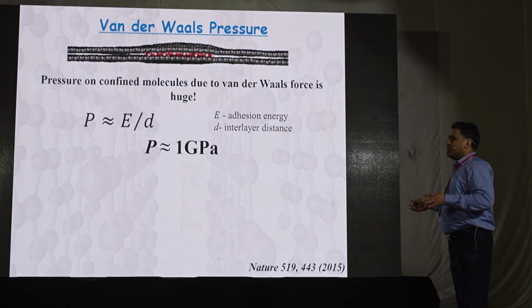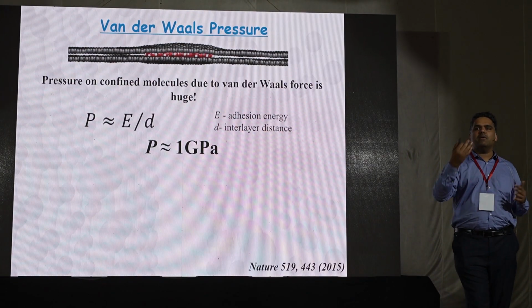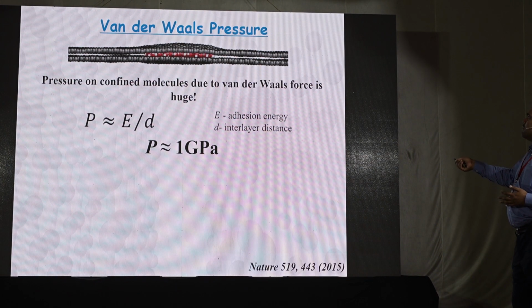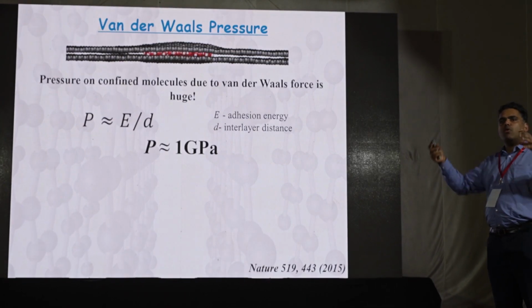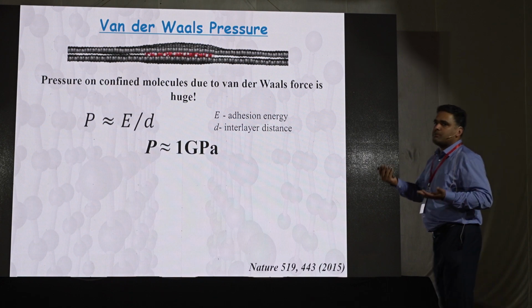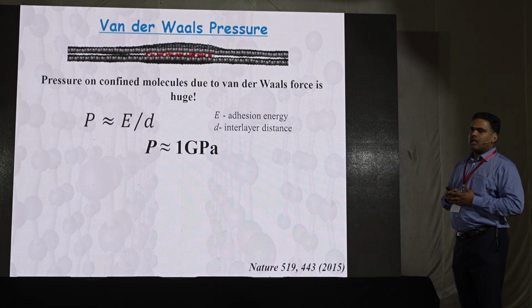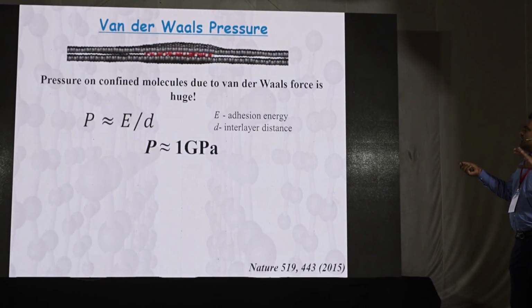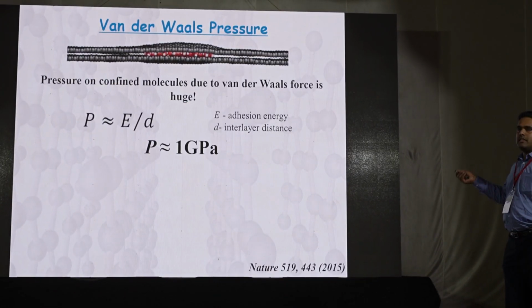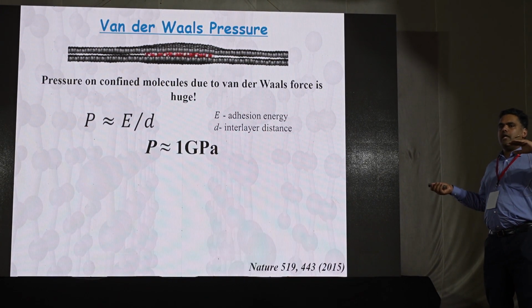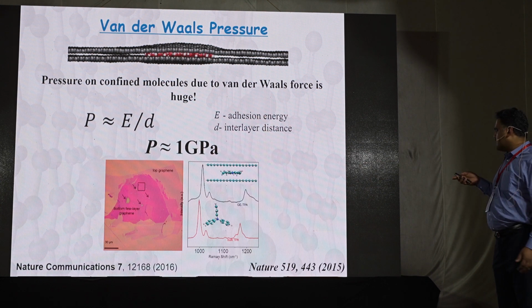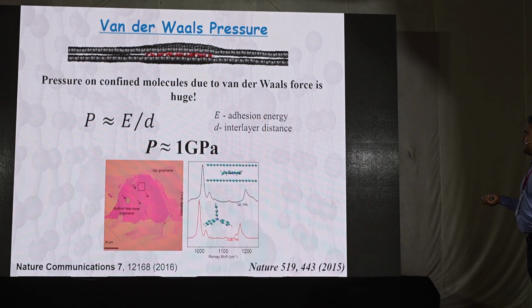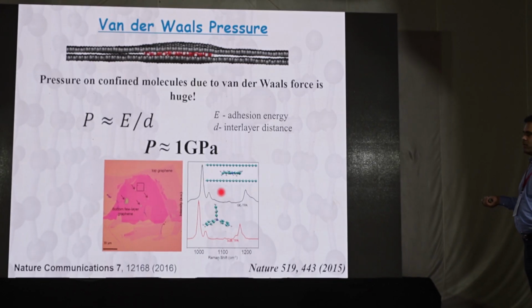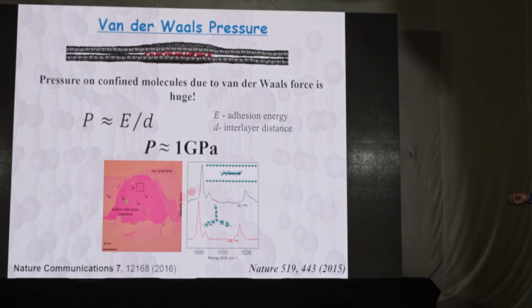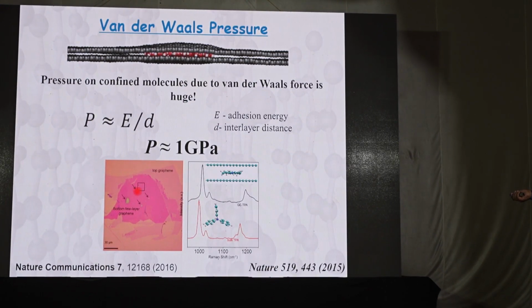So what we did in that sense is we purposefully made this kind of confinement-induced reaction. You take 2 graphene layers, put some molecule in between the layers, and we found that these molecules inside this pocket experience huge pressure, like 1 gigapascal of pressure. The size of this gap, or the pocket, is around 1 nanometer. It's like a couple of layers of molecules. It could be water or organic solvents and so on. We did this by confining certain organic molecules, called TPA molecules, and even boric acid between two graphene layers. And notice that these molecules experience 1 gigapascal pressure at room temperature.